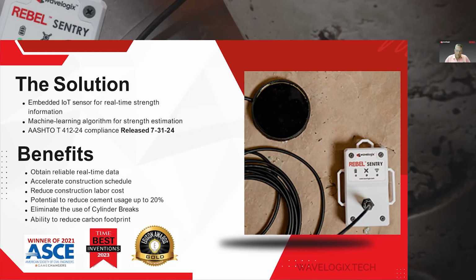Benefits again, very reliable real-time data. We can accelerate construction schedules. We can reduce construction labor cost. There's a potential for reducing cement usage by 20% in this industry. We have kind of a rule of thumb that we over cement by 20 to 25% to guarantee that we get to specified strength. By using our sensors and looking in real time, we believe that over time, contractors can start to reduce the amount of cement that they're using reliably.